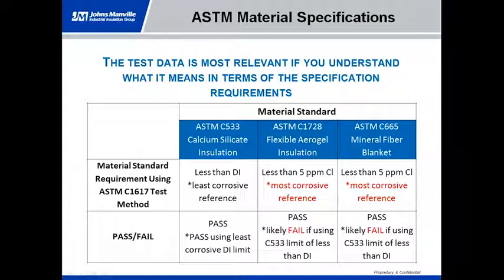And maybe one example of this is that we've talked a couple times about standard specifications for insulations. So if you look at the blue boxes at the top of the table, we start with the ASTM C533, which is calcium silicate, and their requirement is that the corrosion has to be less than the DI water reference, and in this case it does. And as we saw in the previous slide, it's significantly lower than what that threshold is.